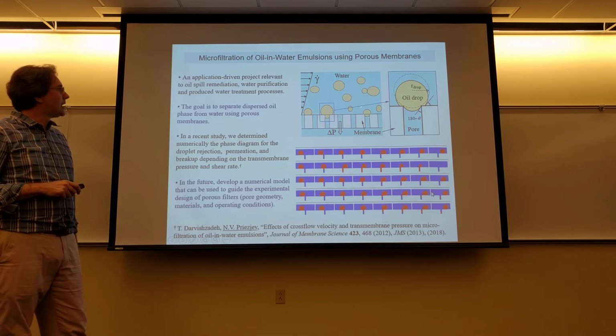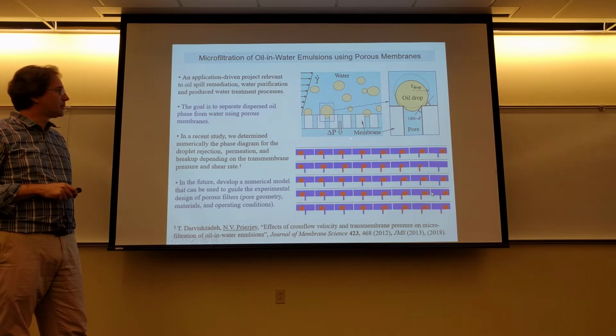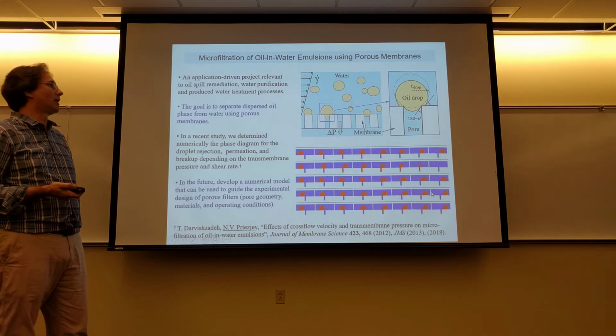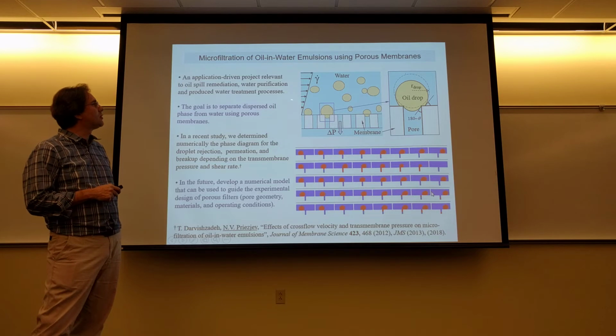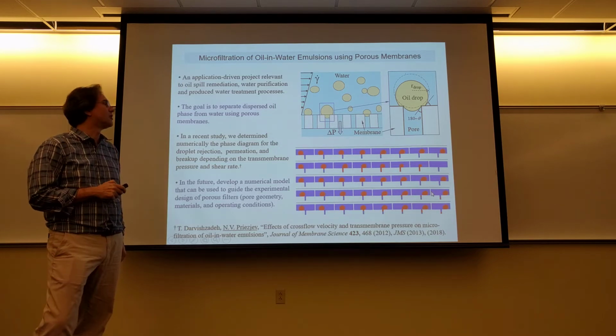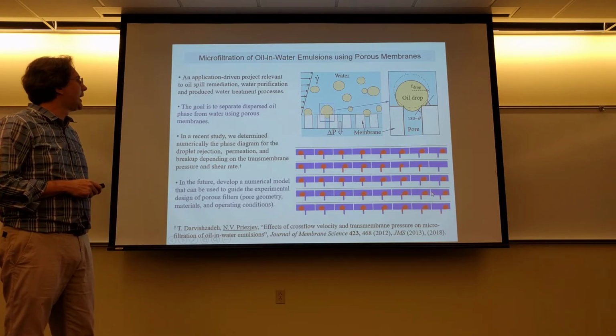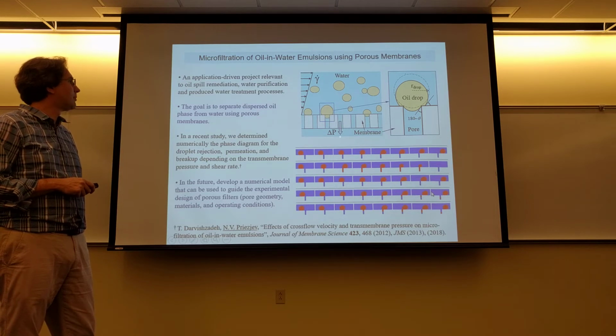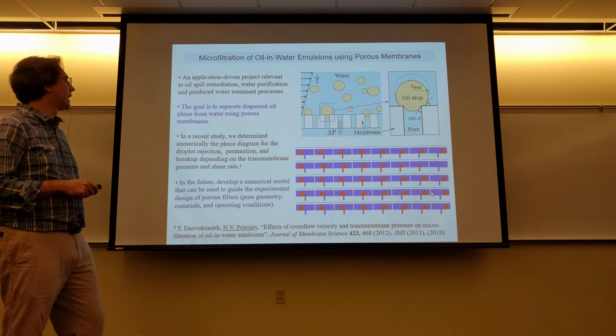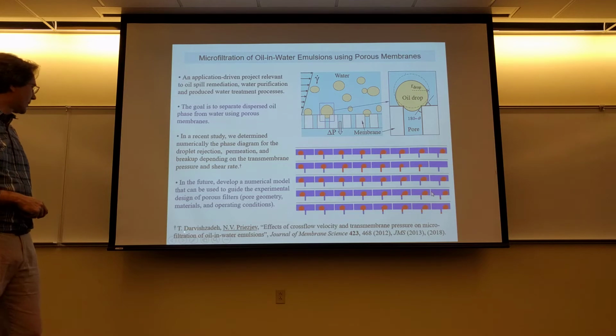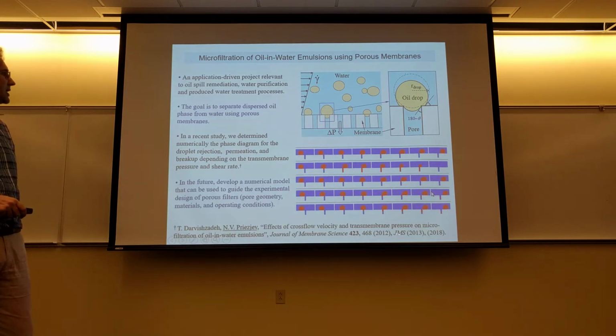Now, the problem here is that under a relatively high pressure, these droplets will leak through and the membrane doesn't work. One way out of this is to introduce a cross flow parallel to the surface of the membrane and induce maximum water flux. And that's what we've done with a student of mine in several papers.